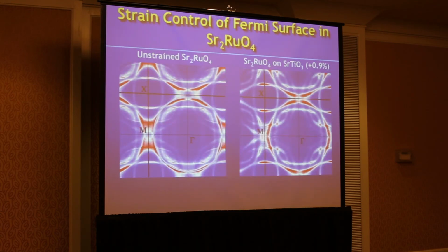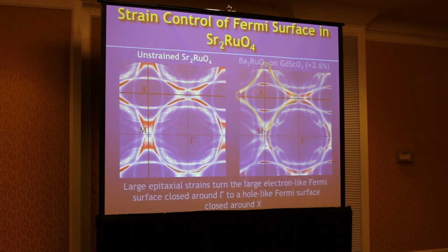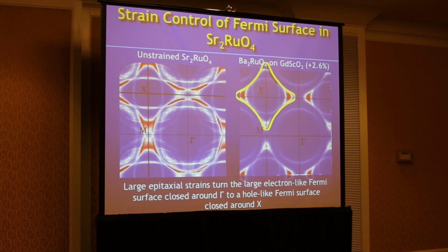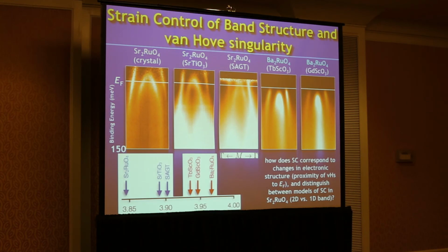And this shows you the band structure. So I showed you before comparing strontium ruthenate that's unstrained. Here we're straining it. Okay, we're getting closer to the Lifshitz transition. Here we've gone past the Lifshitz transition by straining the ruthenium oxide plane by more than 2%. What was an electron pocket here has turned into a hole pocket over there. Okay? Here you can see a series of substrates. And you can see directly, this is the energy axis here, this band, which goes from being below the Fermi level to being above the Fermi level. So you can see as we traverse that Lifshitz transition